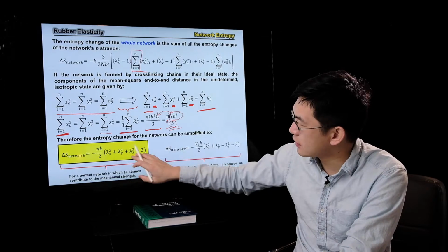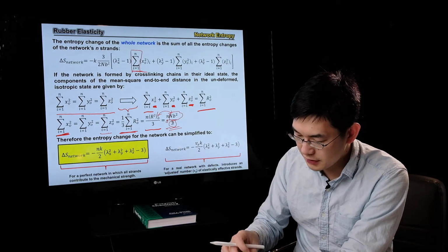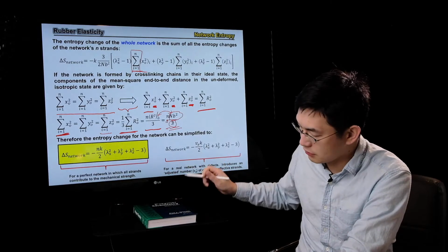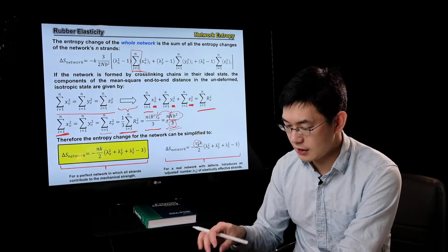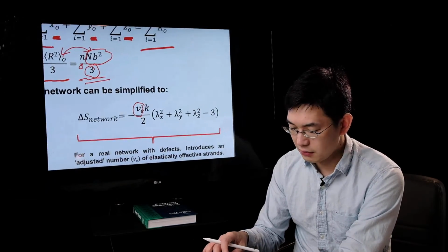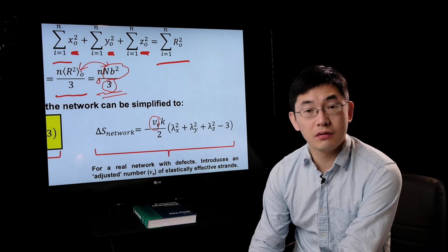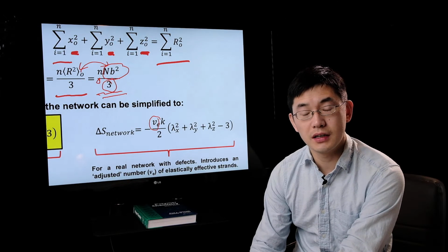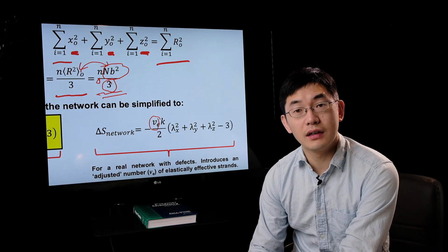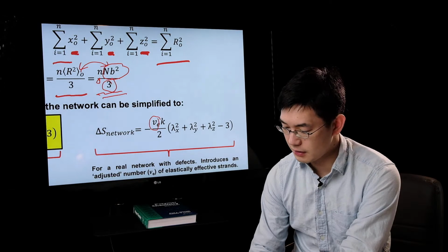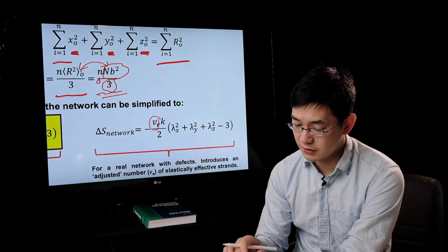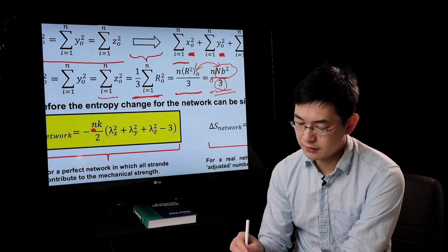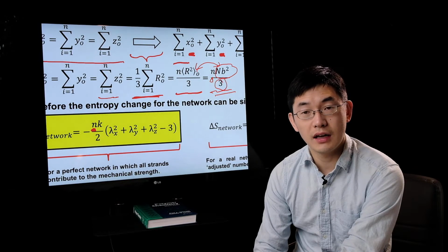We wrote two different equations. The difference is one we wrote as n, the other we wrote as VE. This comes from the reality that for a real polymer chain, there are always cross-link defects. Some part of the strain is not contributing as much as the other. So that's why we need an effective term to come into play here. That's where the VE is: the effective cross-link network density versus your cross-link density in general.